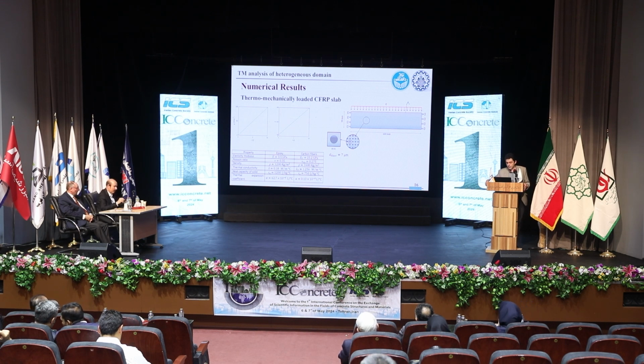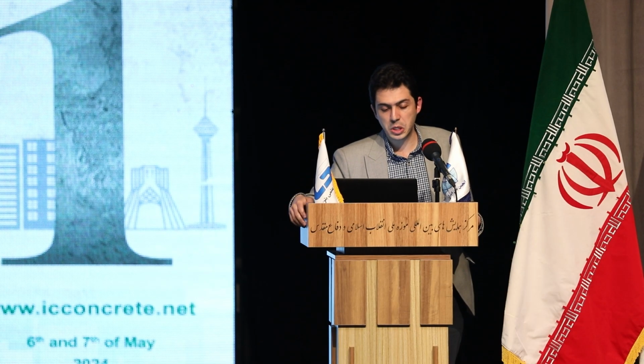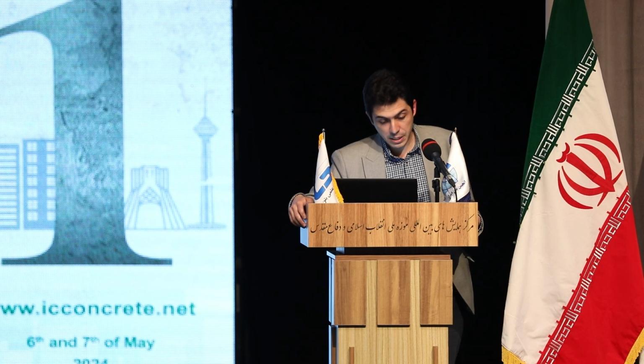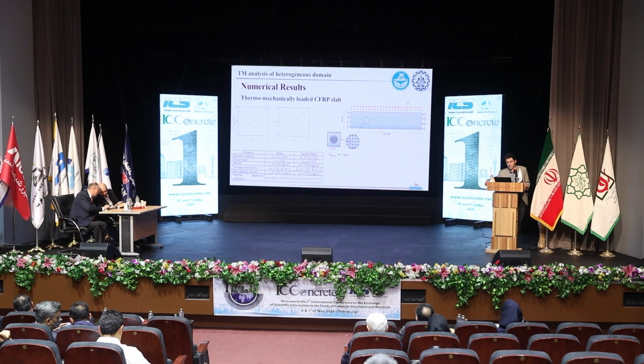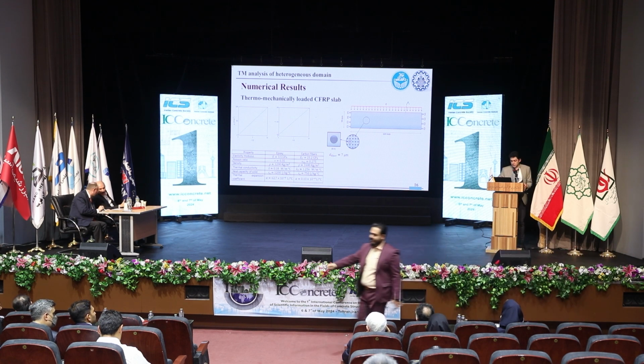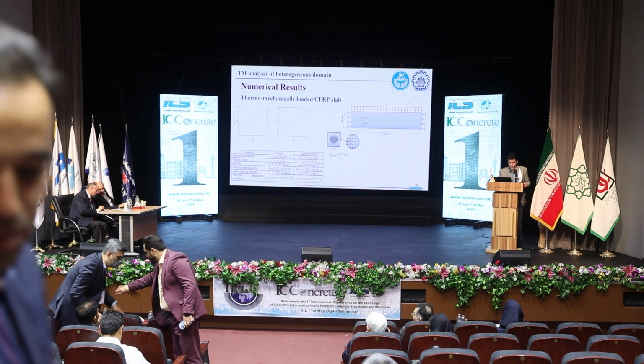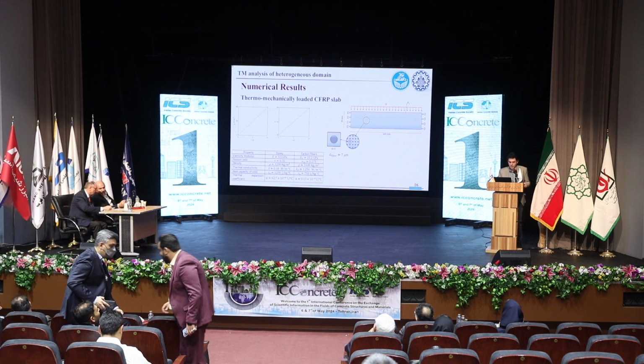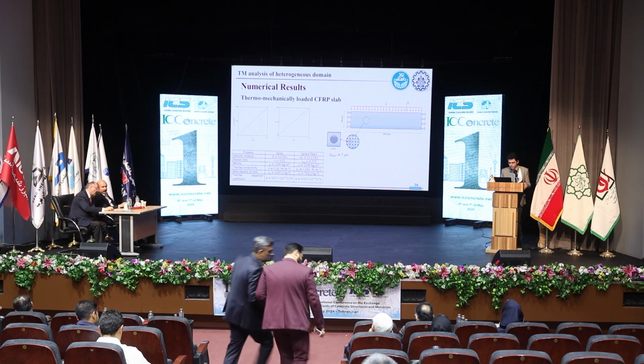So the dimensions are obvious. The diameter of fibers is considered to be 7 micrometers. The distributed load is increased from 0 to 100 Newton per square meter in 10 seconds, and it is kept constant until a steady state solution is achieved. Simultaneously, the temperature of the top surface is increased by 190 degrees, again in 10 seconds, and it is kept constant until the steady state solution is achieved. The thermal and mechanical properties of the materials are given in this table.